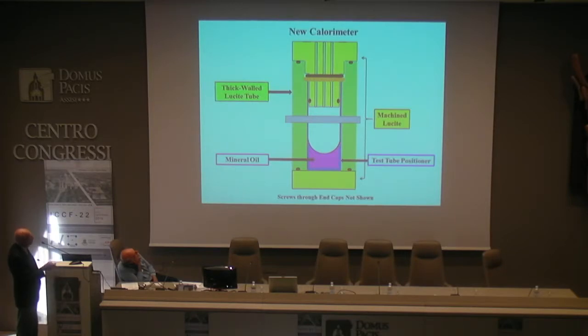Here's a cross-section of it. We use mineral oil as the coupling medium between the test tube and the thermal barrier. We have a 3D printed structure in the bottom here to keep the test tube centered. It's worked out quite well.